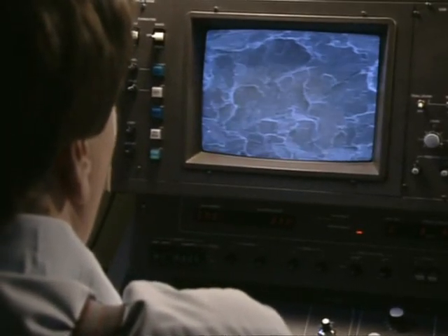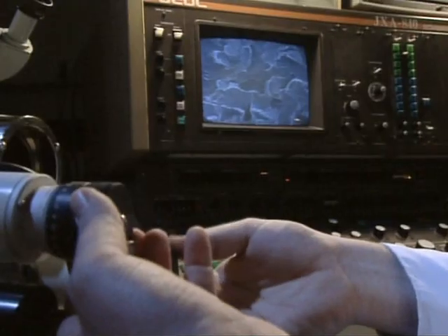Foecke's tests confirm that Titanic steel, with its weak manganese sulfide areas, became more brittle when subjected to the cold temperatures. The fracture surface shows 95% of the grains in the sample cracked. The lines of the fracture trace back to the weak spots in almost every case. So you see the effect of manganese sulfide particles on the fracture behavior of this steel.